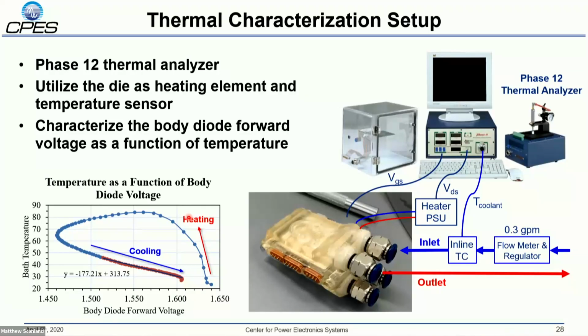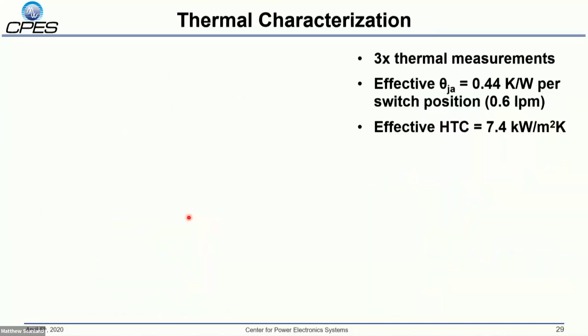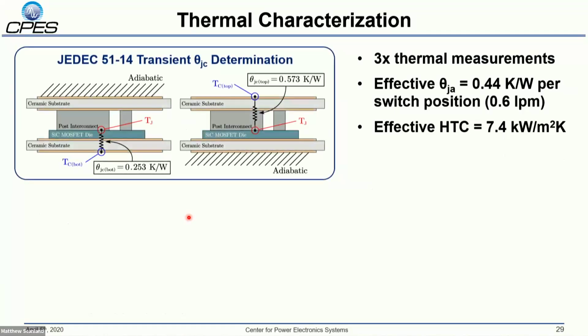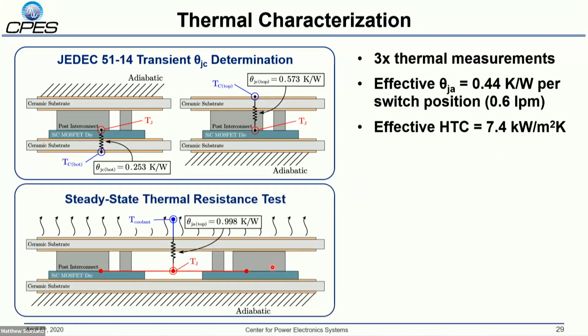So we can heat up the device by conducting through the channel, shut the heating current off, and measure the forward voltage drop to detect the temperature. So there's 3 measurements in total that I took on this system: 2 junction to case thermal resistance measurements, one from the bottom side here and one from the top side, just like Matthias did, with the extra addition of this junction to ambient thermal resistance measurement for the total system.